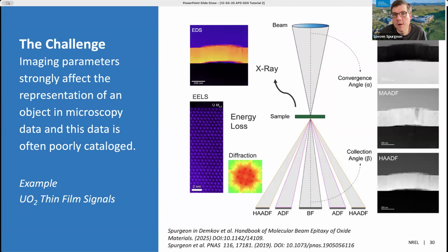So what you're seeing on the periphery here, on kind of the left side, the colored images, and then the grayscale images on the right, are all the exact same sample. This is a uranium dioxide material, and what we're seeing on the top left is an X-ray measurement telling us about interband transitions, core shell states in this material. On the left, we're seeing electron energy loss spectroscopy. On the bottom left is a diffraction pattern of the crystal structure. And then on the right, we have bright field, medium angle annular dark field, and high angle annular dark field imaging, which all give us different sensitivities to the microstructure.